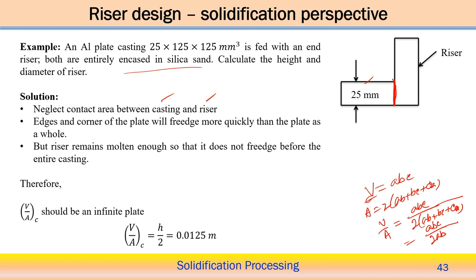So in this case AB is approximately C by 2, because BC tends to 0, CA tends to 0. So, only 2AB will be there, then it becomes C by 2. So, volume by area ratio: there, the volume by area ratio is basically the height, the thickness of this mold. So, H by 2, and this we can calculate, this is the value.